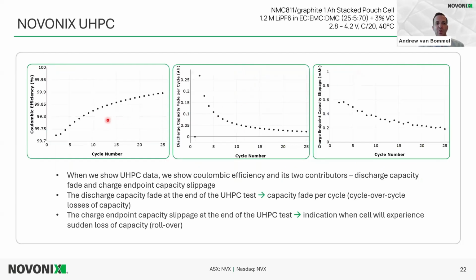So normally when we plot coulombic efficiency, which is the ratio of discharge to charge, we plot it as coulombic efficiency versus cycle number. So during this test period, about 3 weeks, we see that this goes to about 99.9% coulombic efficiency, and it usually just evens out at this level. And we could see its different contributions to the coulombic inefficiency, which would be 100 minus the coulombic efficiency. So here's the discharge capacity fade per cycle. So we see the cycle over cycle capacity fade, at least at this rate, at this temperature. And then we could also see that charge endpoint capacity slippage.